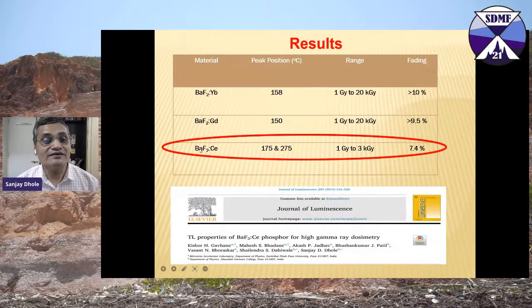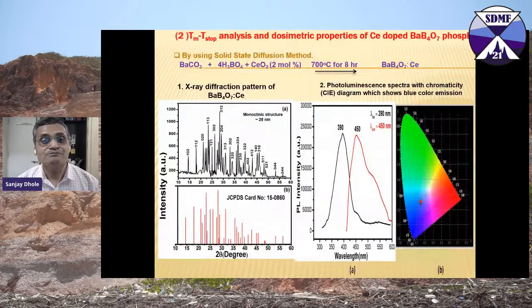So this is the result. Barium fluoride doped with cerium is one of the good candidates which can measure 1 gray to 3 kilogray, and 7.4% is the fading. And this is quite acceptable.